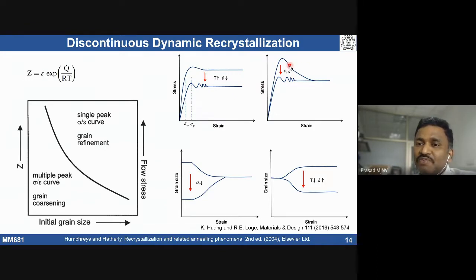So that's what happens if we take a coarse grain and a fine grain. In a coarse grain, the boundaries are fewer compared to fine grain, so recrystallization happens only at certain boundaries. In a fine grain, multiple recrystallizations can happen, and complete recrystallization can happen because a lot of grain boundaries are there. Then again we see work hardening of those recrystallized grains, and the cycle repeats in a fine grain system. In coarse grain material, it is partly recrystallized, and with deformation the recrystallized fraction slowly increases and after a certain time gets saturated, meaning everything is fully recrystallized. So that's the effect of temperature, prior grain size and Z values.